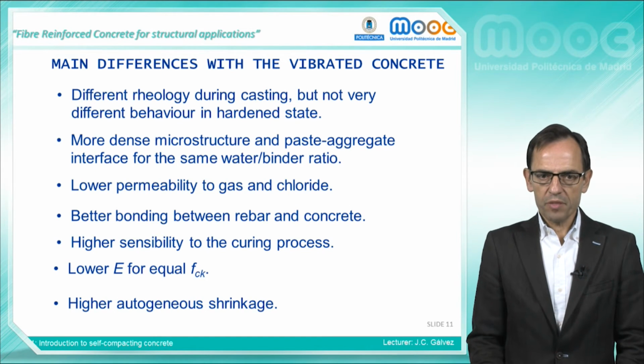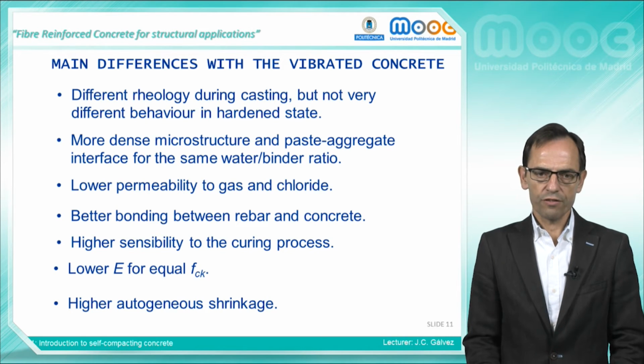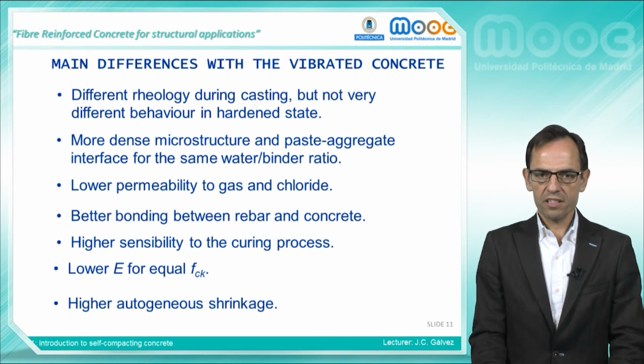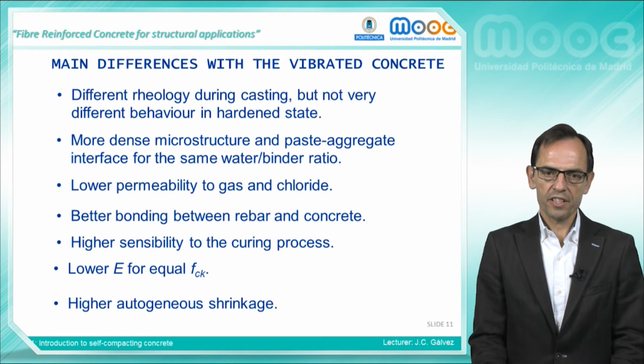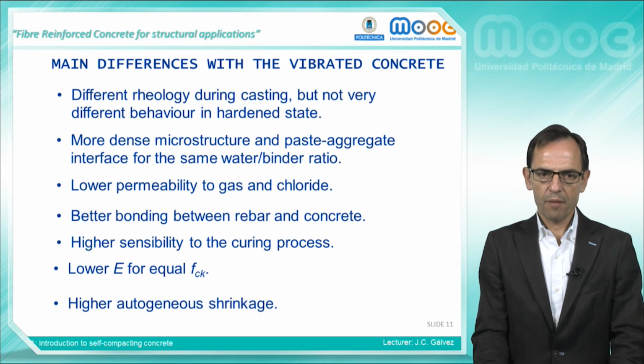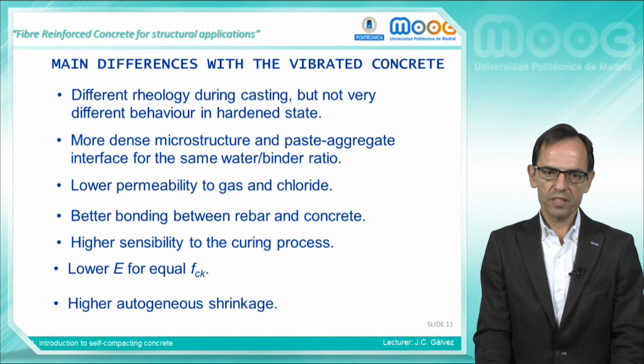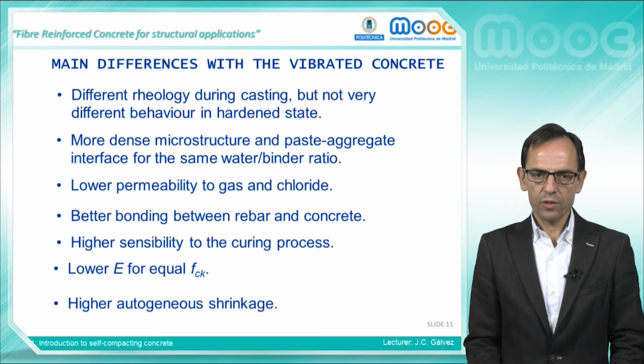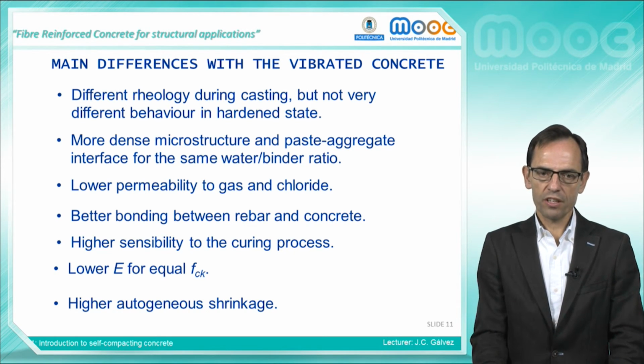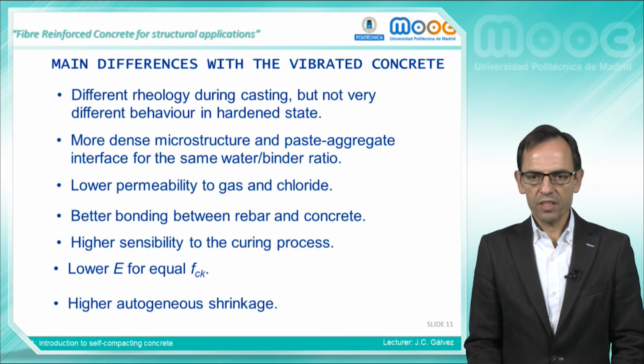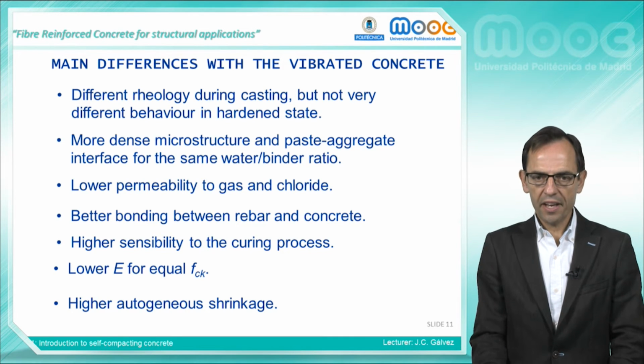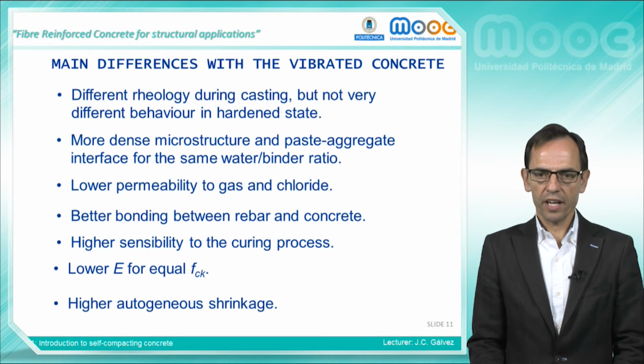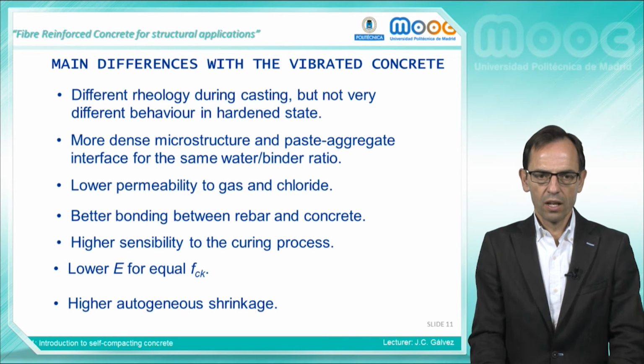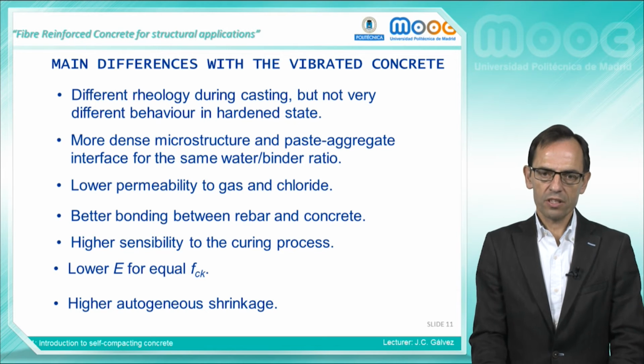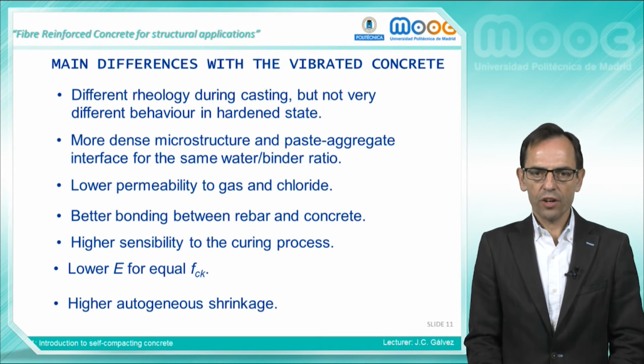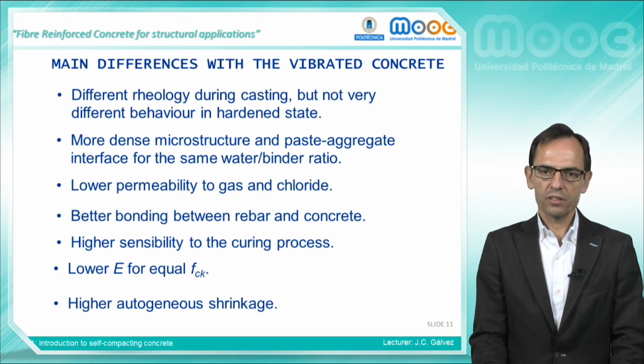The main differences between vibrated concrete and self-compacting concrete are the following. Different rheology during casting, but not very different behavior in hardened state. More dense microstructure and better aggregate interface for the same water binder ratio. Lower permeability to gas and chloride as a consequence of the closer microstructure of the cement paste. Better bonding between rebar and concrete. Higher sensitivity to the curing process due to the higher content of cement and additions. Lower modulus of elasticity for equal compressive strength. And higher autogenous shrinkage rates, also due to the higher content of cement and additions.